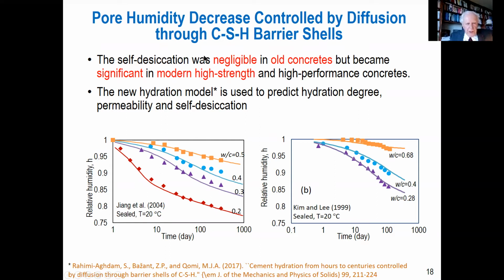Even if the specimen is sealed, humidity is going down. Now, if you have lots of water in the pores, in old concrete, water cement ratio being 0.5, 0.6, self-desiccation used to be neglected because it was known long ago it goes only a few percent below saturation. But in modern concretes, where we use to achieve high strengths, we reach much less water. It is significant. Self-desiccation can go to 75%, and in some, we believe even to 60% humidity in a sealed specimen.